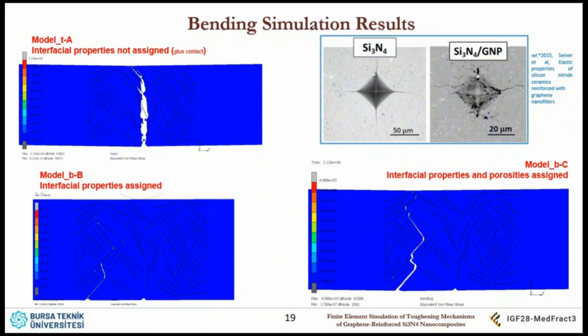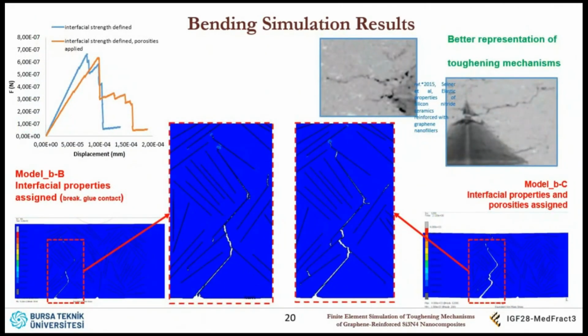Okay, and this is for bending simulation. These results, similar crack path is seen. So this is straight when the interfaces are perfect, but when we apply weak interfaces, we get these. But this one again has got more zigzags. You see, this doesn't jump into the graphenes very well, but this one just touches it, deflects, touches, deflects. And also there's some, if you can see, there's some branching here, but not here. So these are zoomed in images. So this looks more real compared to this.